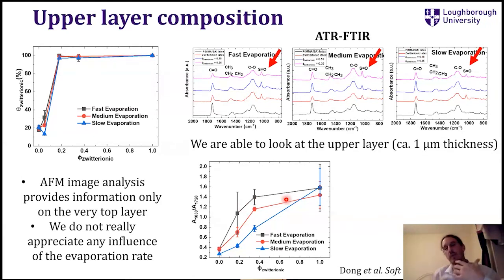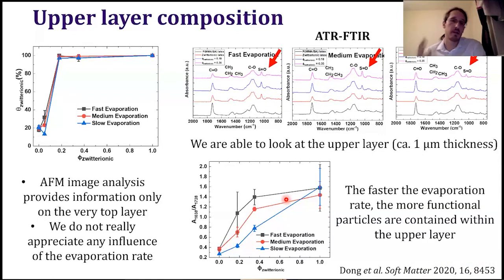So it's overcoming this problem of different drying conditions, because we always end up with the very top surface with what we want to be there, but still the first layer has some of the non-functional particles. Okay, so I think that was one of the challenges that we tried to overcome, and we'll keep on working on that. But it was a good first step in how we can control this stratification in conditions where the evaporation rate is not really predictable, which is one of the main challenges when you're trying to develop a new coating for the market.